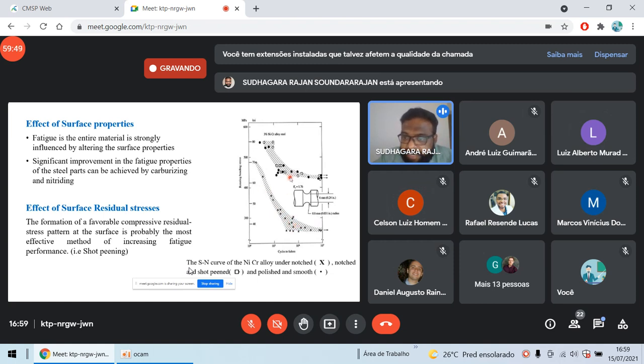But at the same time, if the notched specimen is subjected to shot peening, which is nothing but a process of imparting compressive residual stress in the material, then you can tell in that way: if the notched specimen has a compressive residual stress, then that specimen behaves like a polished specimen without notch. So that's what this entire graph shows you.